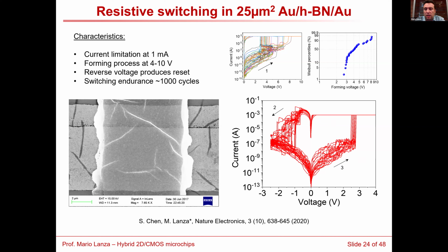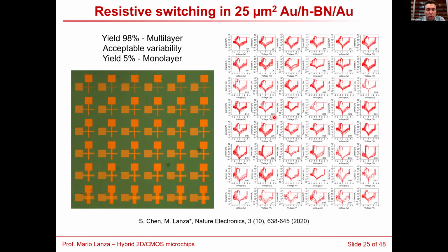With the set and the reset events very clearly here. And we repeat the experiments in many different devices with different sizes, and we observe similar behavior. These are all for the same size. We observe similar current levels and similar switching voltages for most of the devices. Let me also mention that this is when we use multi-layer hexagonal boron nitride with a thickness between 6 and 8 nanometers.